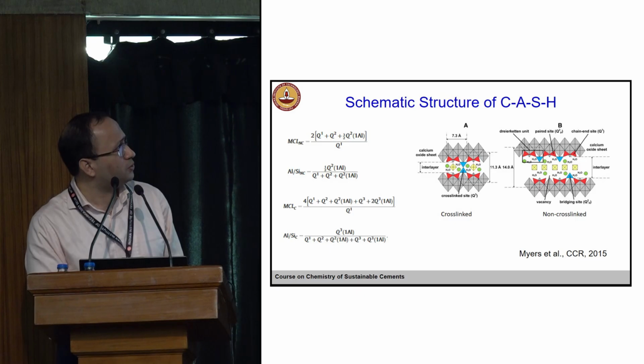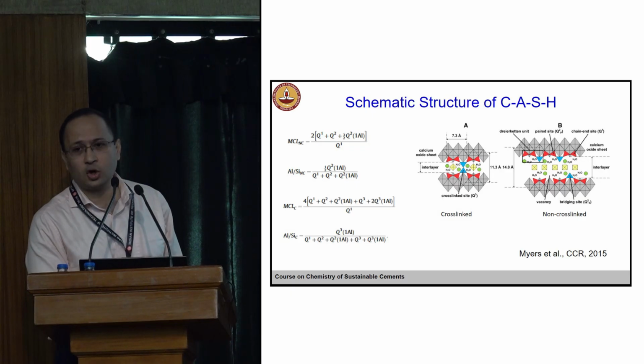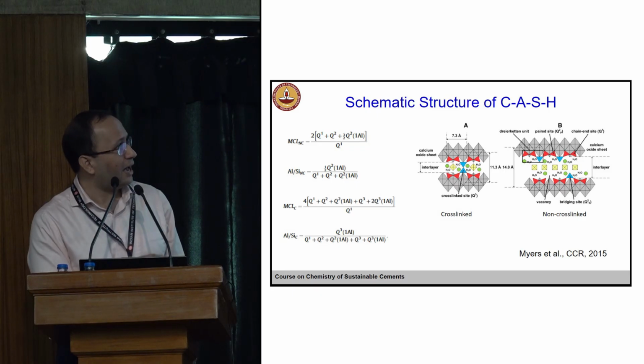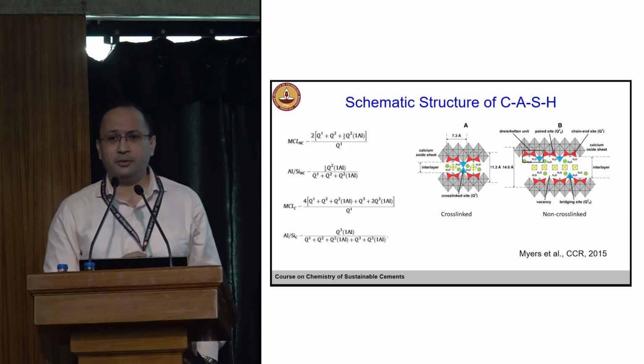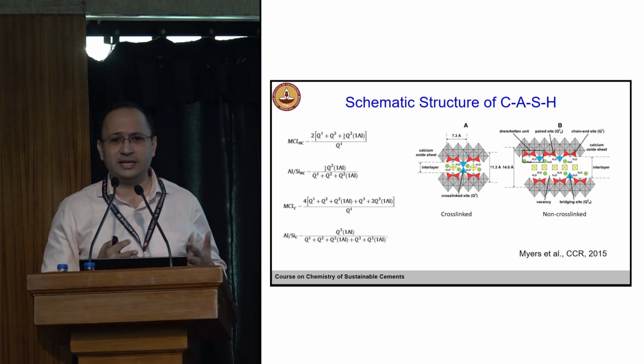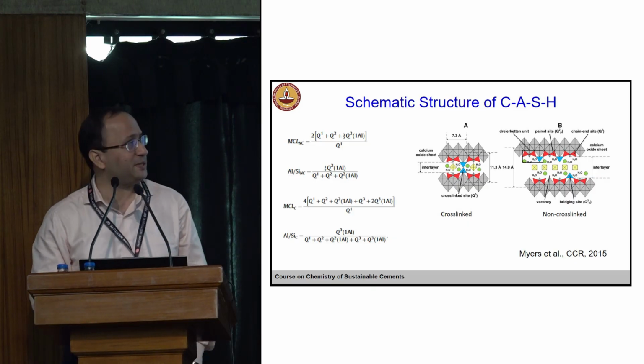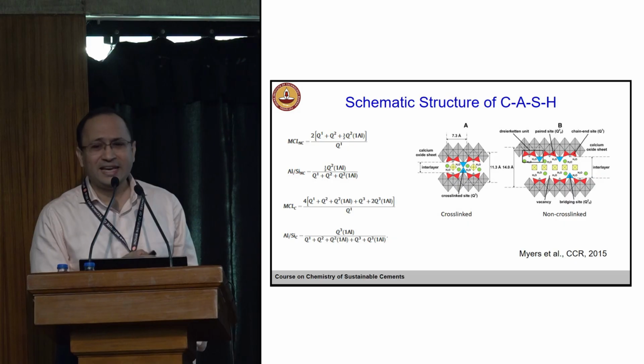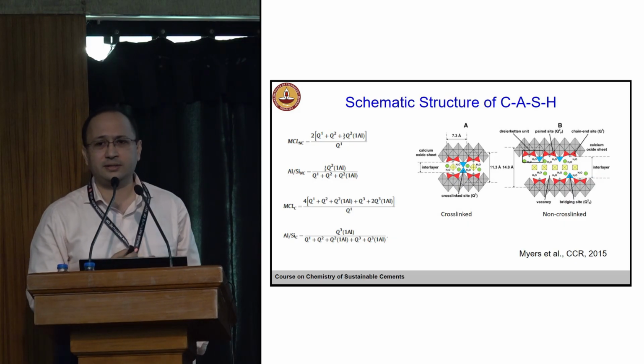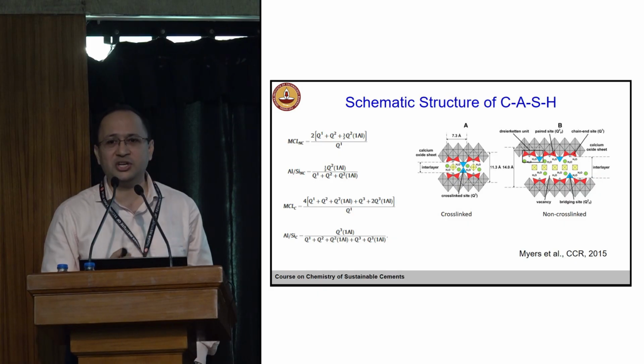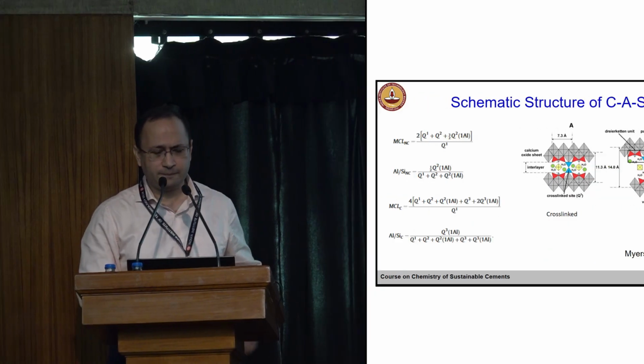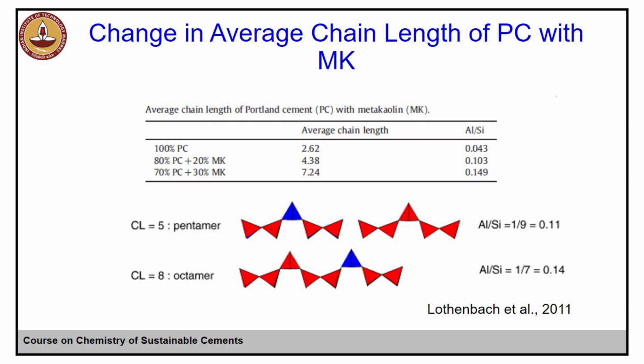So we can calculate the mean chain length, MCL, for non-cross-linked CSH. We can then evaluate the alumina to silica, Al to Si, ratio. I'm not going into detail. Again, for this detail, you can do NMR. From NMR, we can get Q1, Q2, Q3, Q4. These are different coordinations, let's say, of your tetrahedra species. So we can get an idea about how this length is changing when we add SCMs.